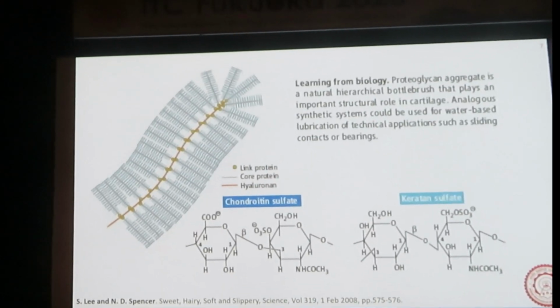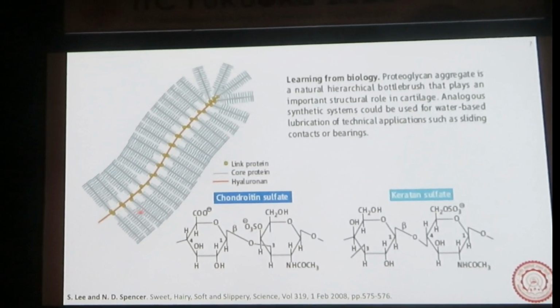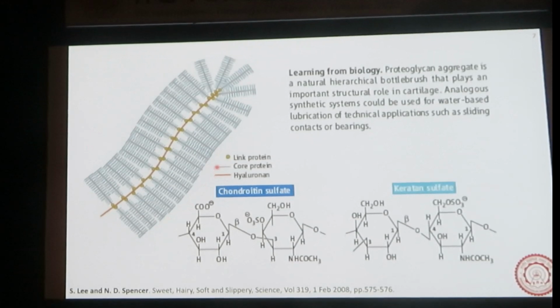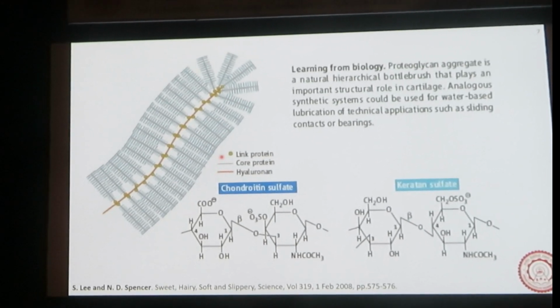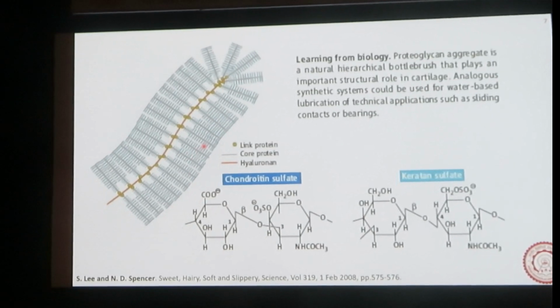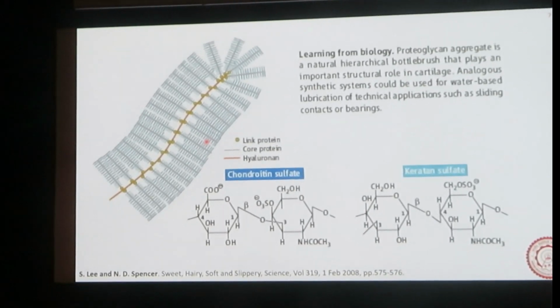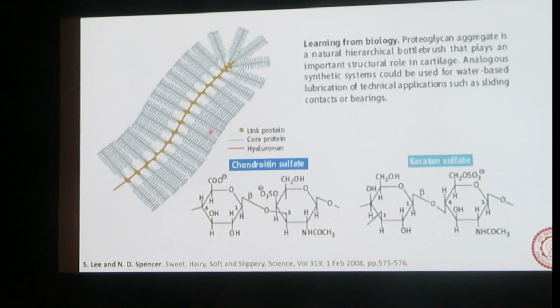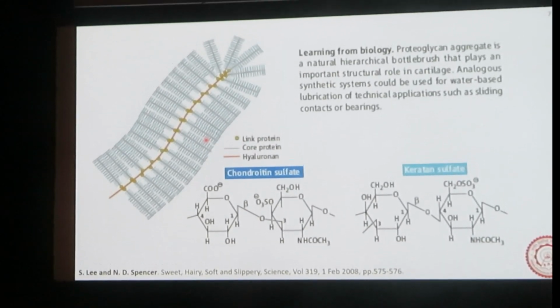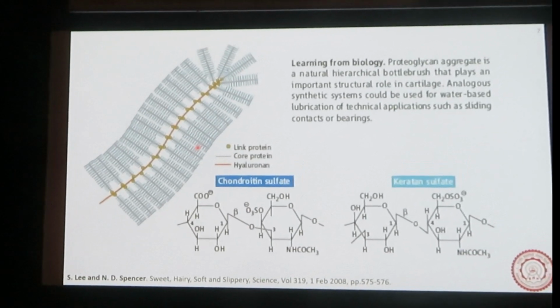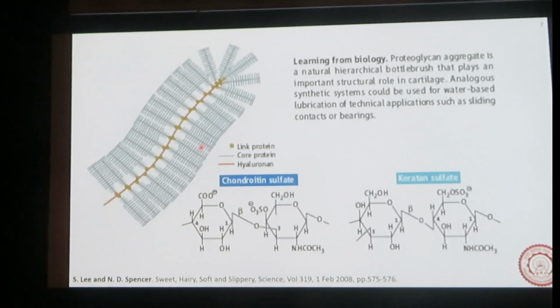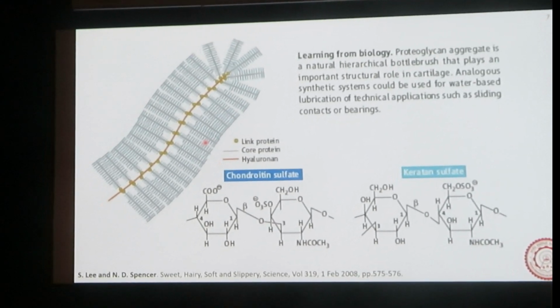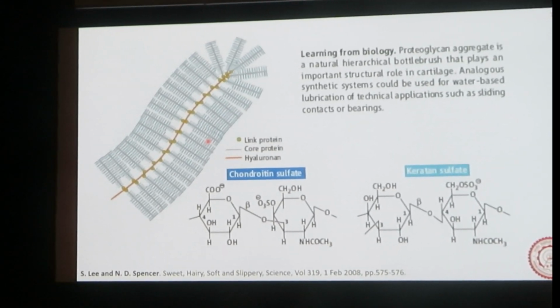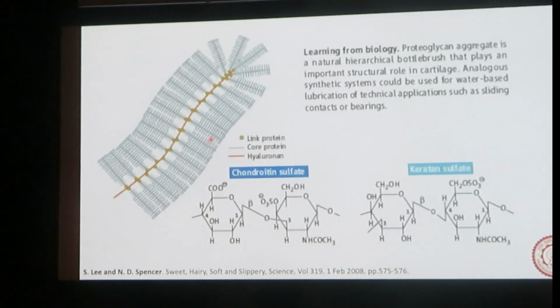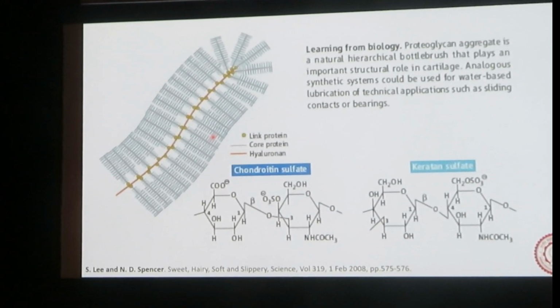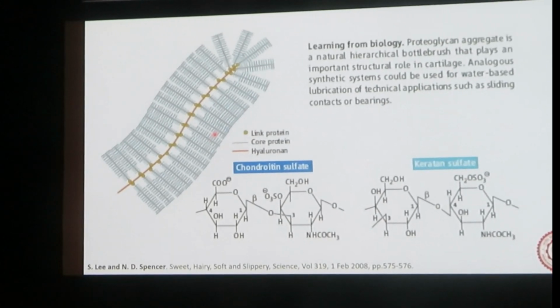And another thing that has been found is that these kinds of molecules have this kind of branching, which is also called bottle brush type of branching. So this branching provides sites where water molecules can attach themselves because of the hydrophilic nature. Overall they are neutral, but they have hydrophilic and hydrophobic surfaces, as well as charged surfaces. Because of this, they can attract water molecules and hold them there. So this is how water lubrication works. And actually in nature, water is used as a lubricant, not oil.